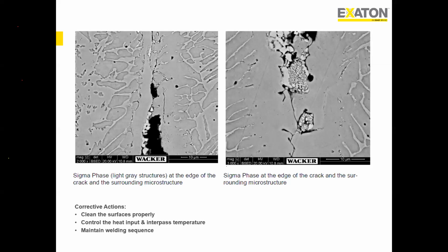They were trying to measure the interface temperature with a laser. For the duplex family, measuring interface temperature with a laser is absolutely wrong because it gives a huge amount of deflection and an absolutely wrong reading. They measured the interface temperature as below 150 degrees centigrade, but when we made a simulation and tested with a contact type thermometer, we found the real temperatures were around 250 to 300 degrees centigrade. That gives an extremely slow cooling rate, and hence this kind of microstructure.